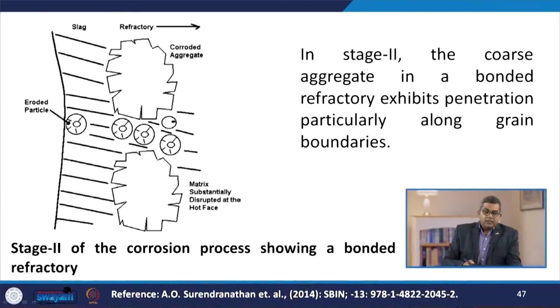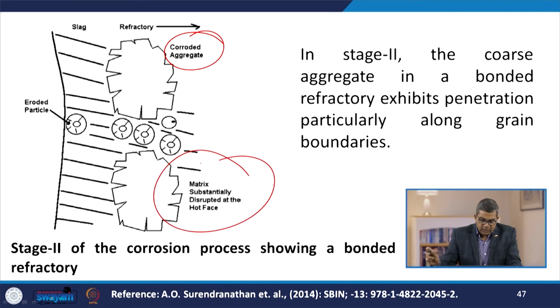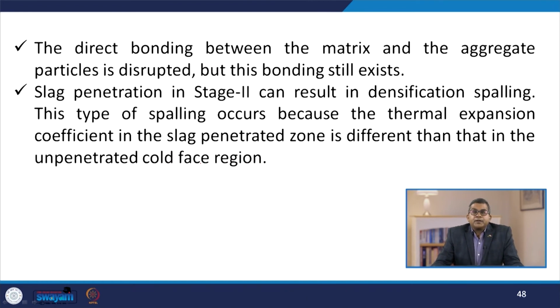Here you see stage 2 of the corrosion process, showing a bonded refractory. In stage 2, the coarse aggregate in the bonded refractory exhibits penetration, particularly along the grain boundary. Here you see the corroded aggregate, and the matrix is substantially disrupted at the hot face. The direct bonding between the matrix and aggregate particle is disrupted, but some bonding still exists. Slag penetration in stage 2 can result in densification spalling.